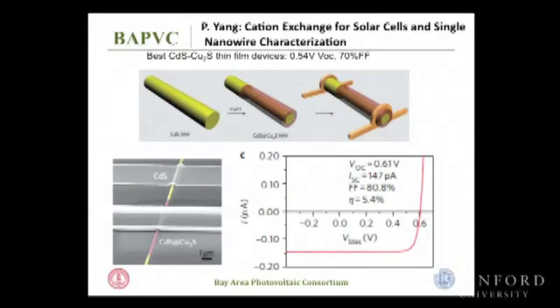In this case, one nanowire is one single crystal. You are forming a cadmium sulfide and copper sulfide junction. This is a single crystal interface. This creates really high performance for the solar cells. This type of information, as a diagnostic tool, can feed back into your solar cell manufacturing to see whether you can promote a similar thing happening to improve your efficiency. So this approach is not only a solar cell, it's a diagnostic tool to understand what's happening and to feed this information back.